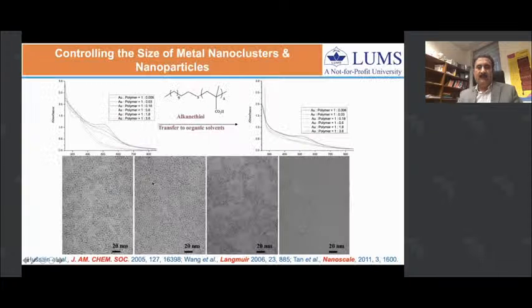In another case, we use this thioether end-functionalized polymer, which has this thioether group and then a carboxylate group to make these particles soluble in water.